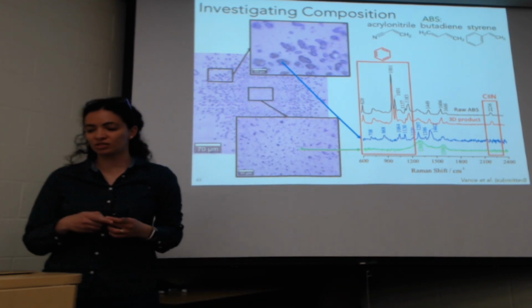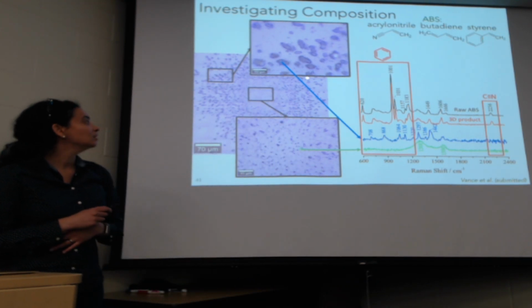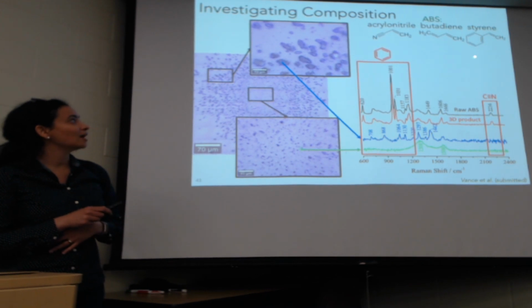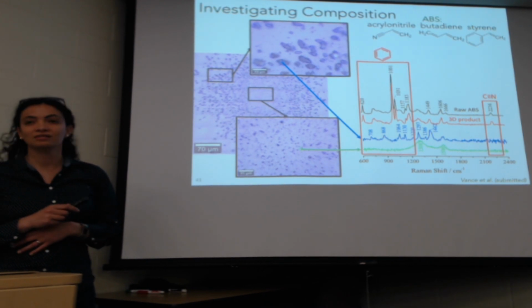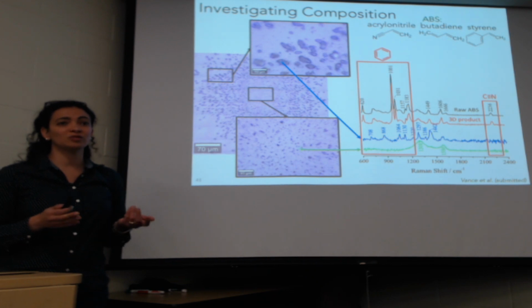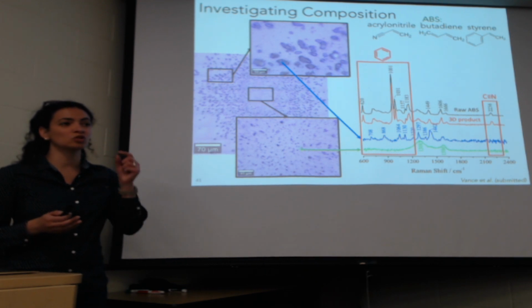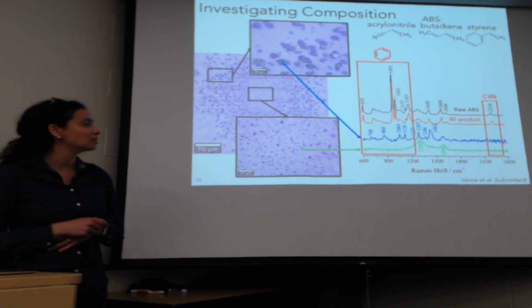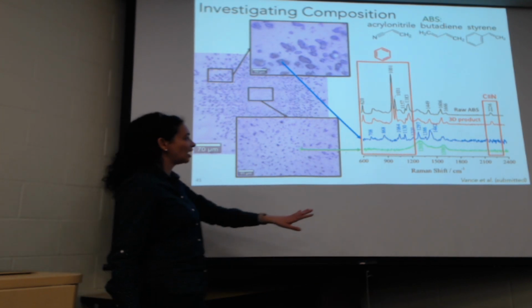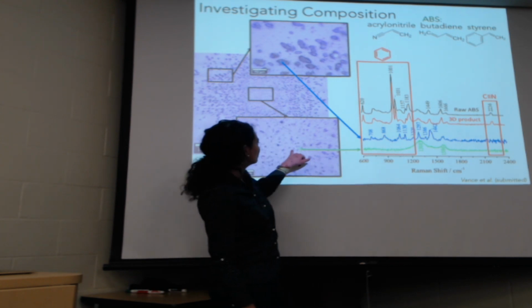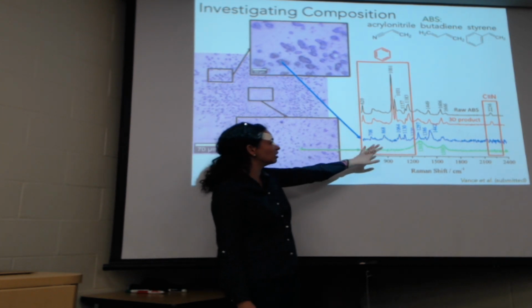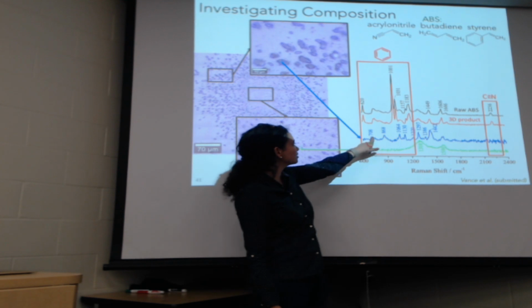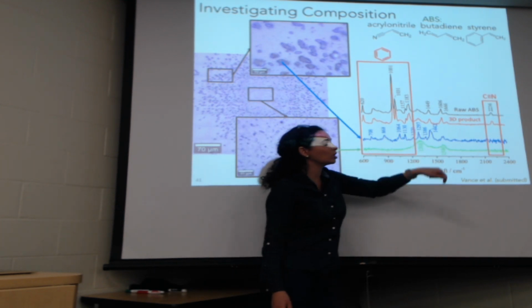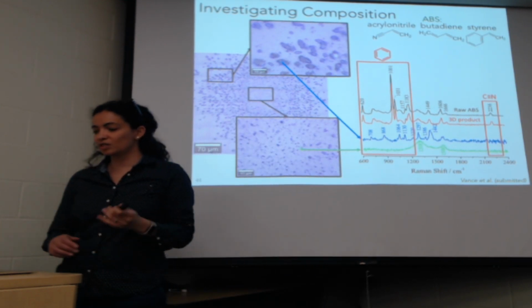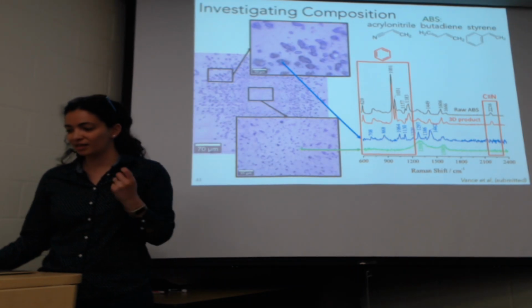So that shows us a theory that these particles are not made of ABS, because they don't have this and they don't have this. It's possible that we were just not able to detect it through Raman. It's possible that there's so little of them that we weren't able to see it. But it's telling us that these particles are made of something else because they have all of these peaks. For the really tiny ones, it was a lot harder, of course, to get a clear signal. But for the bigger particles, we can tell that there's something else. It would take a lot of extra effort to find out exactly what.